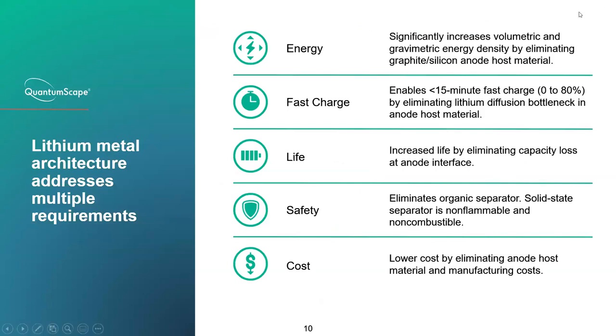So let me come back to these 5 key requirements and explain how the lithium metal solid state separator addresses each one. So energy, of course, by getting rid of that host material, using the pure in situ plated lithium metal, we can increase the energy density no matter which cathode we choose. Charge and power, we can improve by getting rid of this bottleneck at the hosted anode surface. Life, we can improve because, again, some of those reactions taking place at the anode can be improved with a solid state, stable ceramic separator.